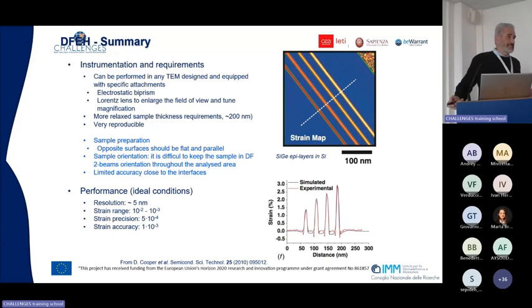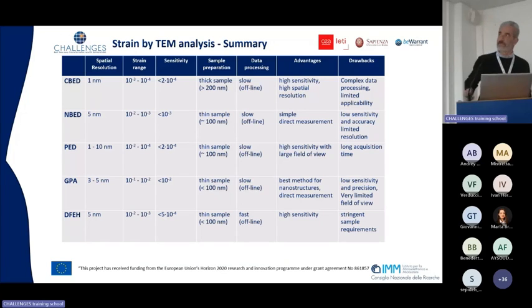You need some experience to operate with this kind of technique, so you need to be quite well trained. It's advisable that your microscope carries a Lorentz lens that can work in place of the objective lens, so it should be designed for this analysis. Again, thickness plays a detrimental role here. You need a relatively thin sample to perform this kind of analysis, and in thin samples we are prone to strain relaxation. You must keep this in mind. So, close to the end, you can read this at home.